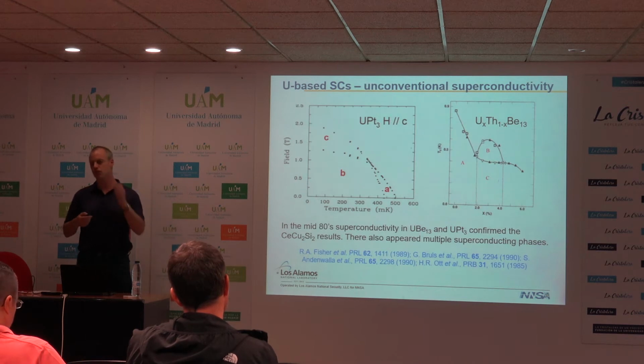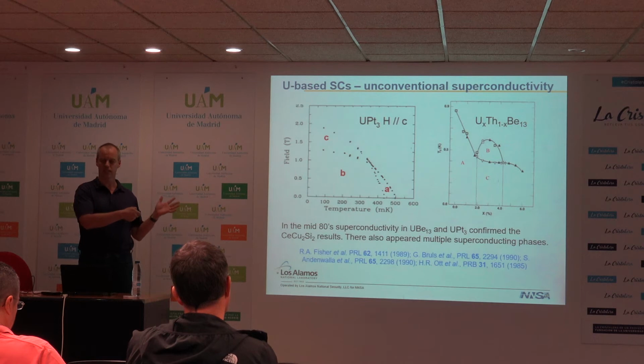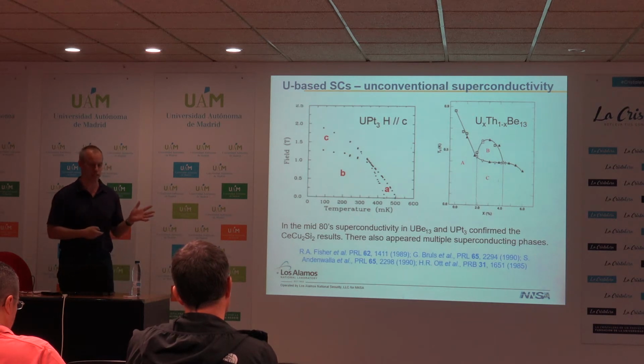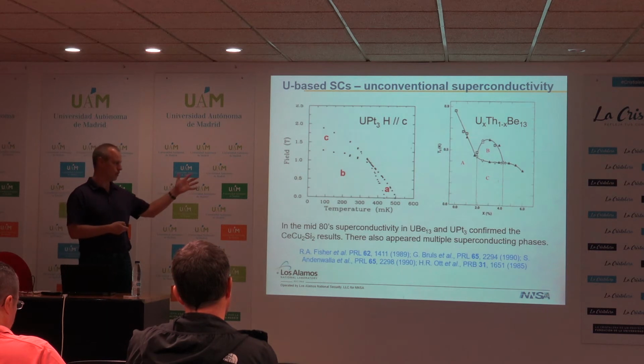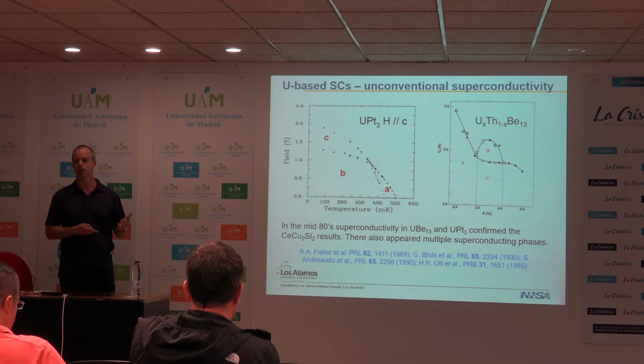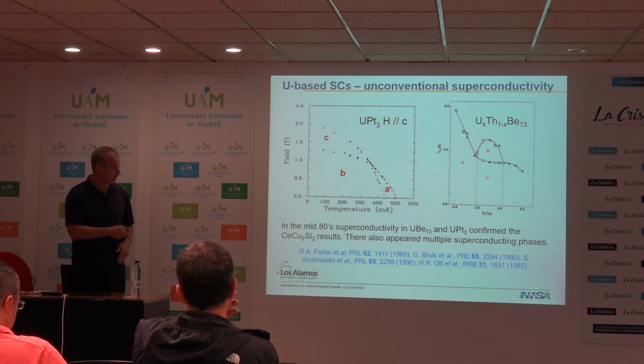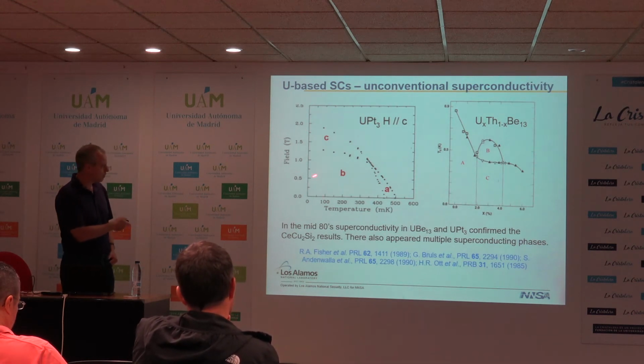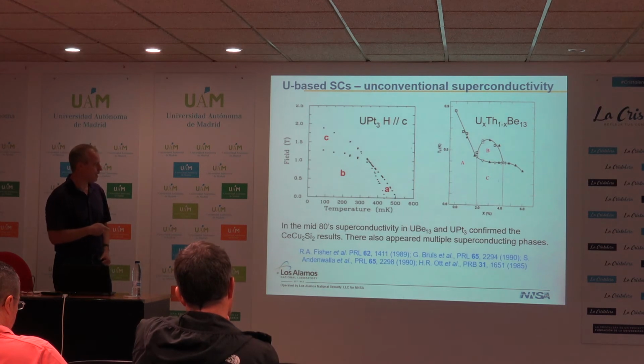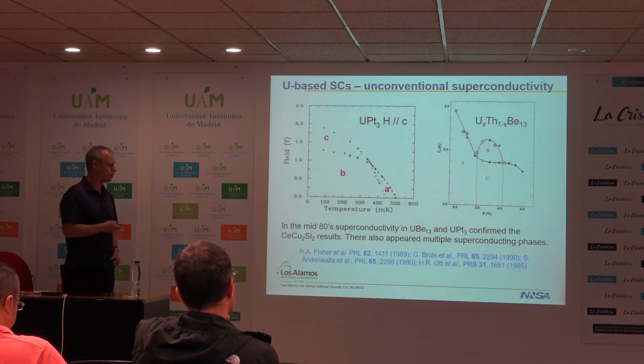And it's very difficult, if you have an S-wave superconductor, to see how you could imagine coming up with 3 distinct superconducting phases. So this was already one of the first evidences that the order parameter must be unconventional in these materials. And in fact, this early work was predating the work on high Tcs.